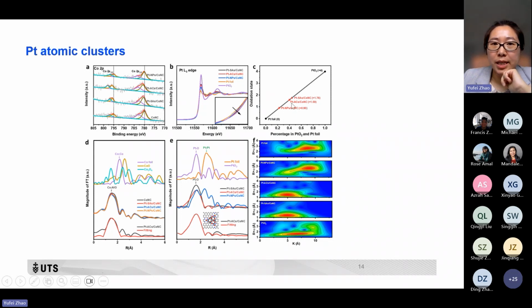Also, we have calculated the valence state of the platinum. After the calculation based on the XPS result, we can see the valence state of the atomic cluster Pt is lower than the single atom Pt. That means the lower valence state of the Pt may possess a higher electron density to facilitate the HER and may achieve better performance compared to the single atom. And for the result for cobalt, we can see there is almost no change after incorporating the Pt species. It still keeps the original coordination environment. So the incorporation of Pt doesn't change the environment of the cobalt.